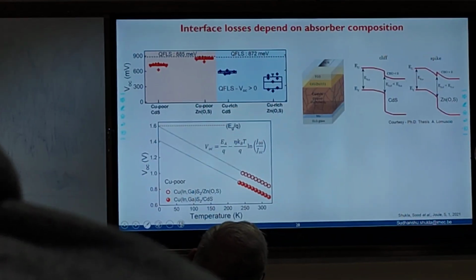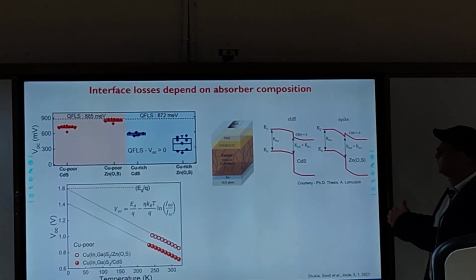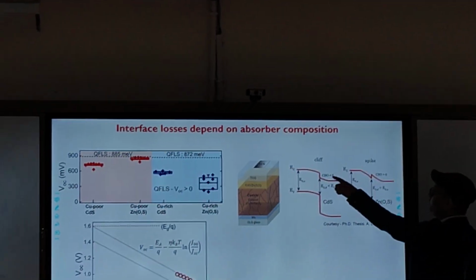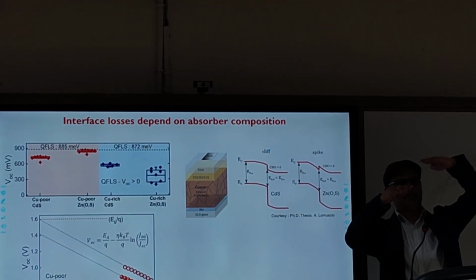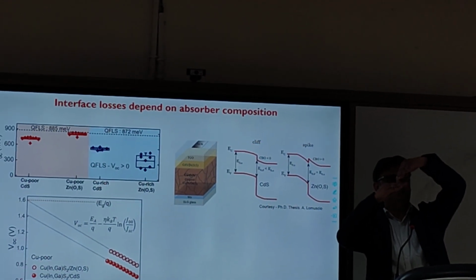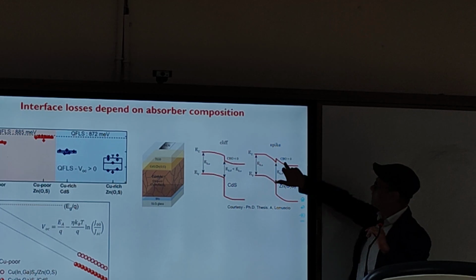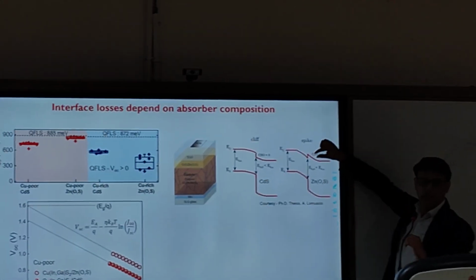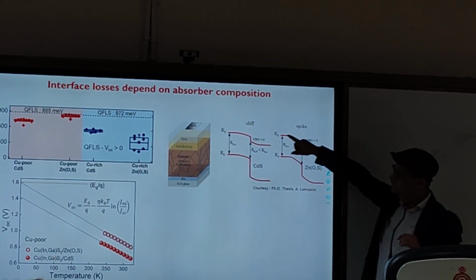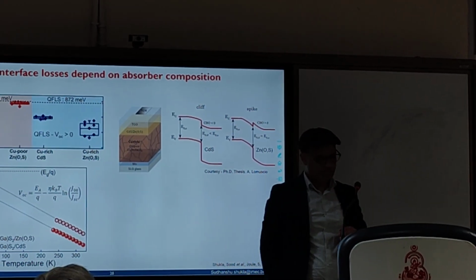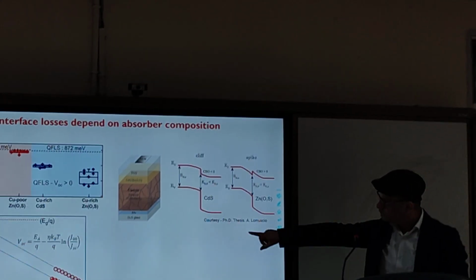And there's some explanation, pictorially, of what happens when you change from cadmium sulfide to zinc oxysulfide. Why interface recombination reduces is because your band alignment changes from cliff to spike. Remember in the beginning I said electron doesn't want to lose its energy. So we change this configuration. So at the conduction band, the electron doesn't lose its energy, and that's why the interface recombination is suppressed. Okay, I'll skip that part.